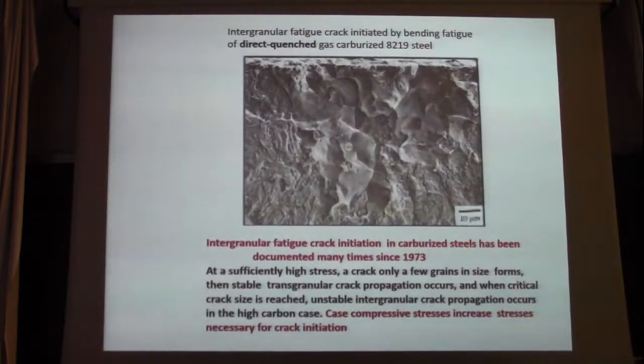And then carburized steels. They have 0.8% carbon at the surface. They're in that quench embrittlement field. And if you get to a stress level where this develops, then you get this intergranular fracture that nucleates fatigue cracks. And then there's also martensite transformation here, causing the crack to go transgranular, be stable, until it reaches the critical size associated with the fracture toughness of the steel.